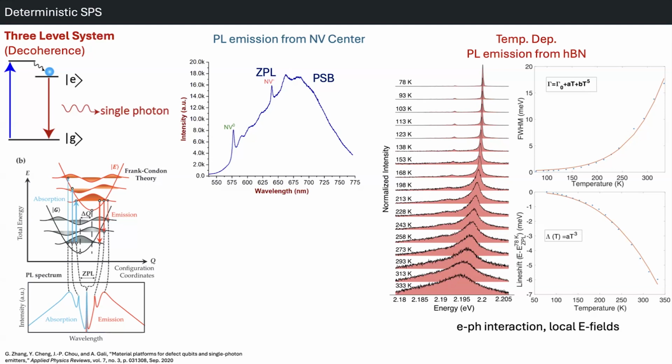Well, like I said, you cannot use it for even a single photon because of the phonon sideband. I'm sorry, the phonon sideband is here, it's just hidden. I didn't show it, but you see the phonon sideband here clearly. NV0 also has a phonon sideband, which means you're losing your pure electronic state transitions to electron-phonon related transitions.